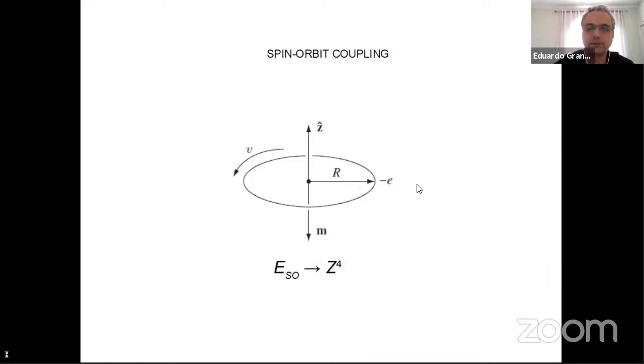That's the physical origin behind that. And it's important to mention that this energy coupling becomes more important for ions which are heavier, basically because of high atomic number. If you have a higher atomic number, first of all, you have more protons in the nucleus, so the charge of the nucleus is larger, and it generates a larger magnetic field. And not only that, but also for heavier elements, higher Z, it turns out that the electronic cloud tends to become closer to the nucleus because of Coulomb interaction. So it's pretty much like you have a circuit which is closer to the center, and so the magnetic field that is sensed by the electron will be higher.